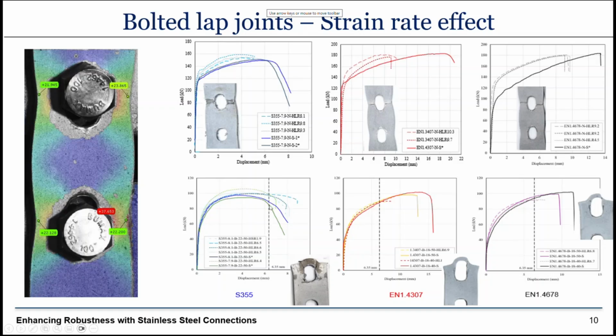We can see that for carbon steel, with increasing strain rate, with increasing loading speed, we have higher yield, higher ultimate stress, and lower ductility. For the stainless steel specimens, for both grades considered, both the conventional and the nickel-free one, with increasing strain rate, we get a decrease in ductility, an increase in yield resistance, but also a slight decrease in the ultimate tensile stress, because the strain rate we induced was similar to the one from the material coupon test that gave us that corresponding drop in the ultimate stress.